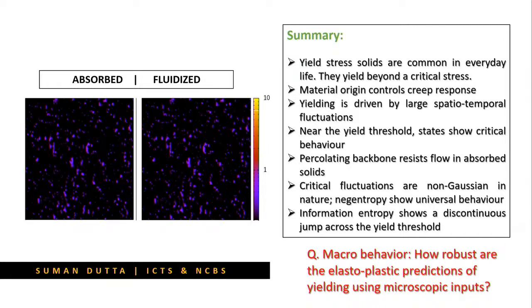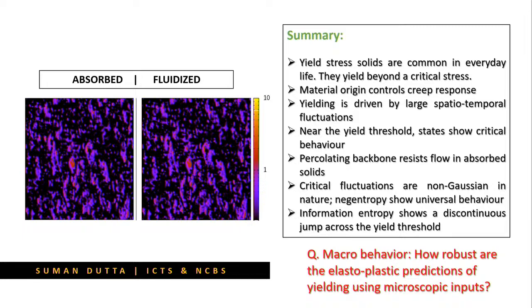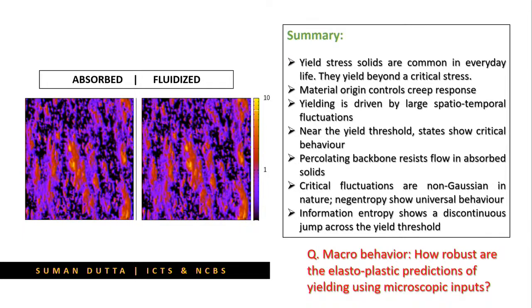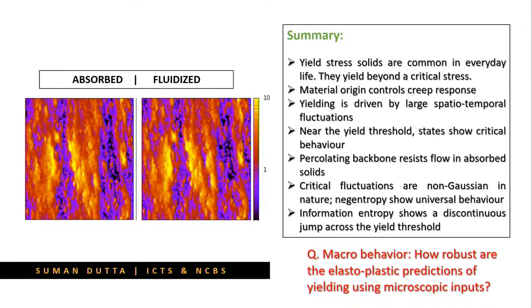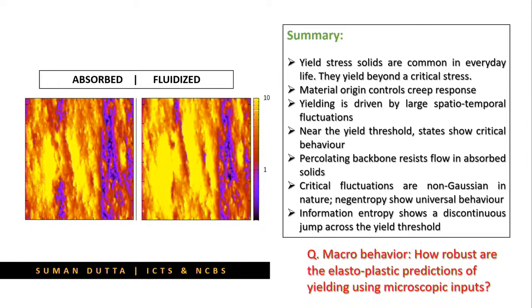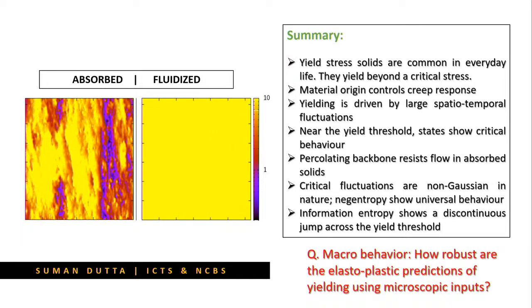liquid. So, in summary, we have seen the yield stress materials, and we will explore them very soon. They yield beyond a particular threshold, and then we showed that different kinds of yield stress materials show different kinds of response, and their material origin controls their creep response. This creep response, and the yielding by this creep, is driven by the spatiotemporal changes and fluctuations, and the system lies in a critical state near the yield threshold.